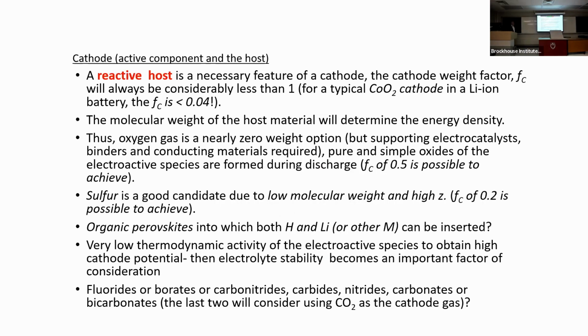Okay. When a cathode is considered, we need a reactive host. So therefore, whatever we do, the cathode weight factor is always going to be considerably less than 1. Say take cobalt oxide, the cathode factor is 0.04, because we need a very stable host. It is the molecular weight of the host material that determines the energy density. That's why when you use cobalt and nickel and manganese and iron, we actually lose control over the molecular weight. It's very, very high.